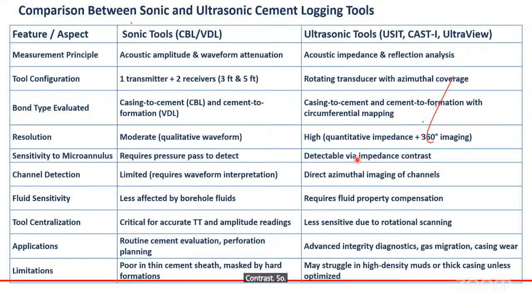So in ultrasonic, if there is any gap, it will appear in the impedance itself. You have a 360 impedance, so you will see the contrast between these ones. Channel detection is limited. If there is a channel behind the cement, there is no cement on it, it's difficult to find it, but in ultrasonic it's a direct azimuthal imaging of channels. Fluid sensitivity: less affected by borehole fluid, requires fluid property compensation. Tool centralization: critical for accurate TT and amplitude reading, less sensitive due to rotation scanning.